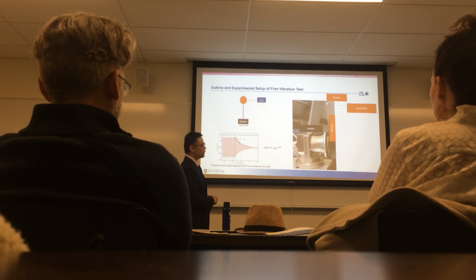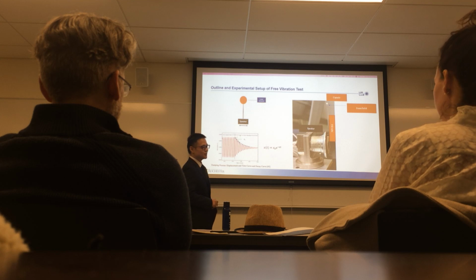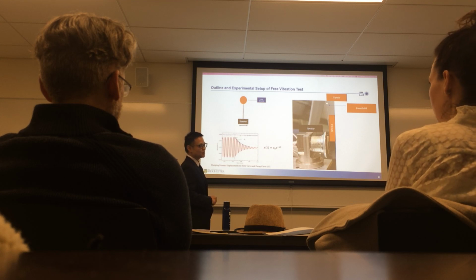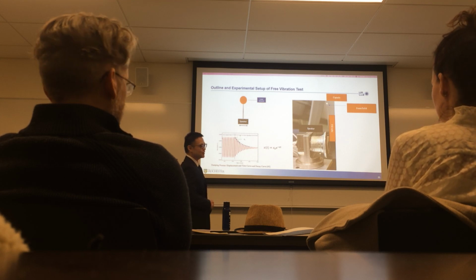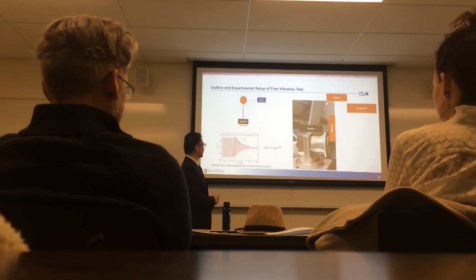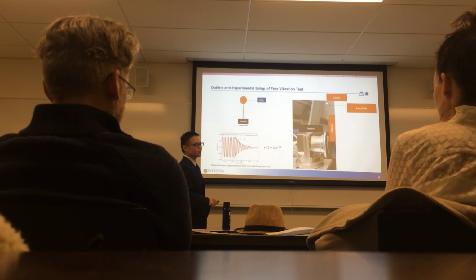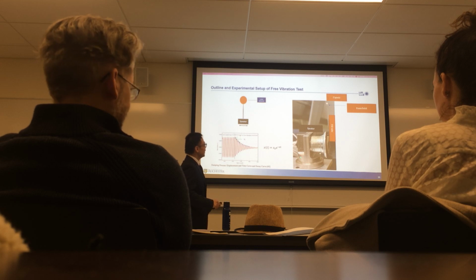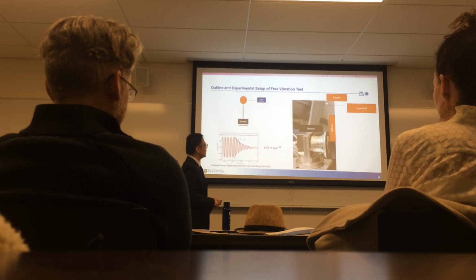When we started finding the vibration source, we used a lot of time because we tried to use a hammer to shake the fuel tube. We tried to use a moving stage to shake the fuel tube, but it's hard to control. But finally, we found a very easy way to control the vibration. Use a speaker from the audio. And this speaker will be controlled by the function generator. This function generator will control the frequency and amplitude for the speakers.